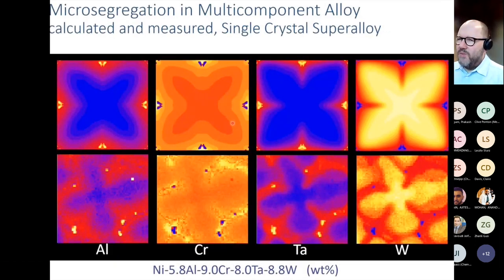If we do this for a simple alloy, simple in terms that it has only five alloying elements, nickel, aluminium, chromium, tantalum, and tungsten, we get patterns like this. For this alloy, we have actually made some alloy, directionally solidified it, and then used WDS to map out the elemental concentrations in a quantitative manner. And then we did simulations for exactly the same alloy composition and the same process conditions as well. And what we end up with is what we see here. So we've got aluminium first, chromium second, tantalum, and then followed by tungsten.